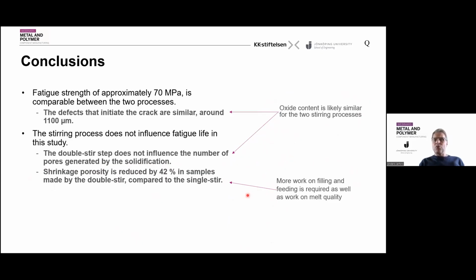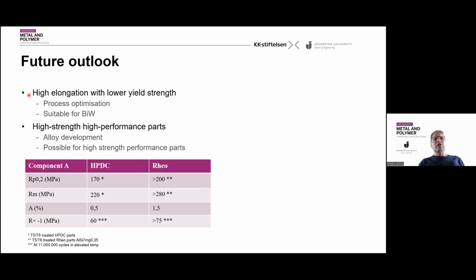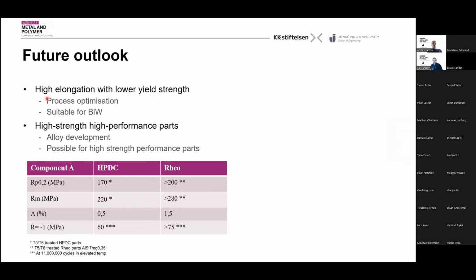And this comes as a rather important part, because if you look towards the future, one thing that we could see is that we could have a better elongation, especially if you have slightly lower yield strength requirements. That means that what you can work with here is the low-hanging fruit, and you can go directly for process optimization and start working with body-in-white type of components. When it comes to high strength performance and high performance parts, there is likely to need further alloy development, since we can have better elongations, we can actually have better crash performance, even if you have a slightly higher strength of the materials.